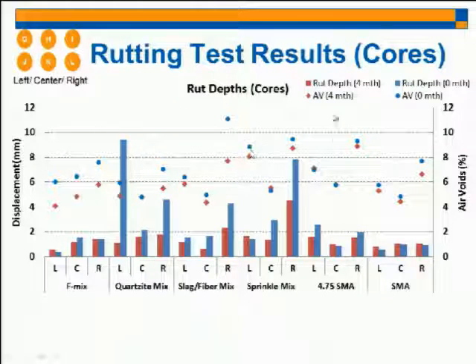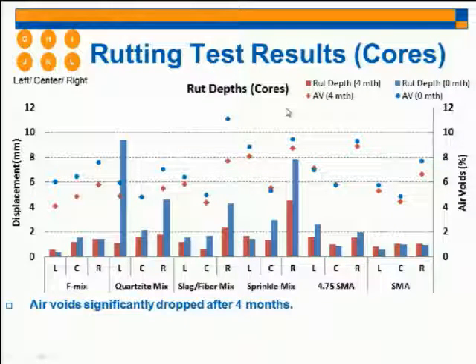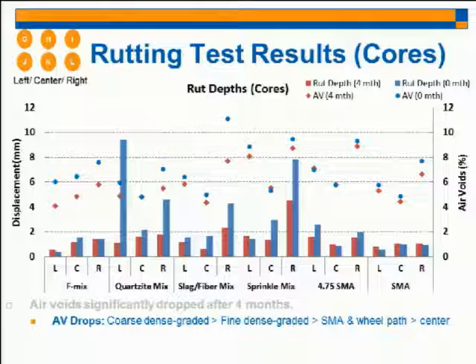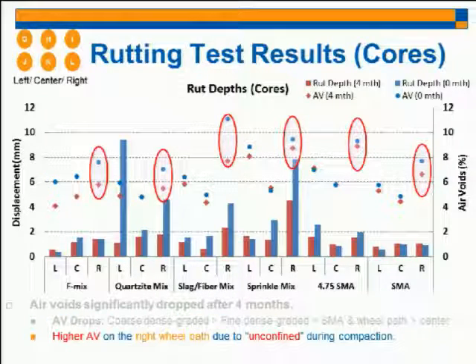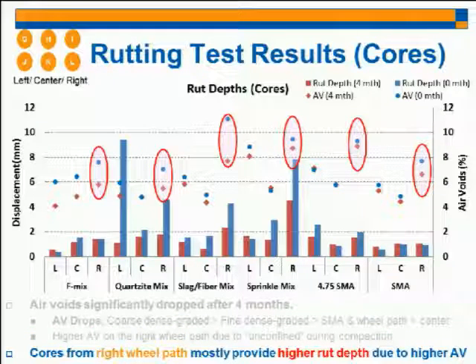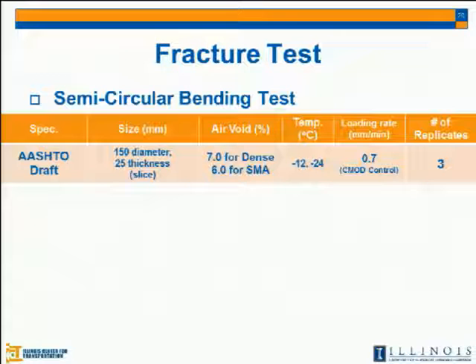And also we took the cores 4 months after construction. After 4 months, the air void significantly dropped, and the coarse dense grade showed a higher air void drop than the fine dense grade and SMA mixture. And the air void in the wheel path dropped more than the center of the lane. Because we have the higher air void on the right wheel path, the rut depth was higher than the center and left wheel path.